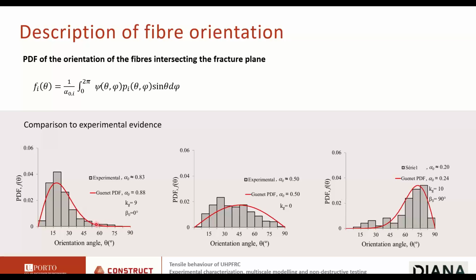So what do we take from here? That when we have well-oriented fibers, so a very large value of alpha 0, we see more fibers with orientation angles close to 0, which, if you recall, means that the fiber is perpendicular to the crack. Okay, so we see very few fibers with large orientation angles. These fibers, as we will see, are sometimes not effective. So if the fibers are well oriented, they are almost all effective. On the other hand, if you go to the other side of the spectrum, if you have a specimen with a very poor fiber orientation, you see that you have a lot of fibers with large orientation angles that will not become effective when you start applying tensile stresses to your material.